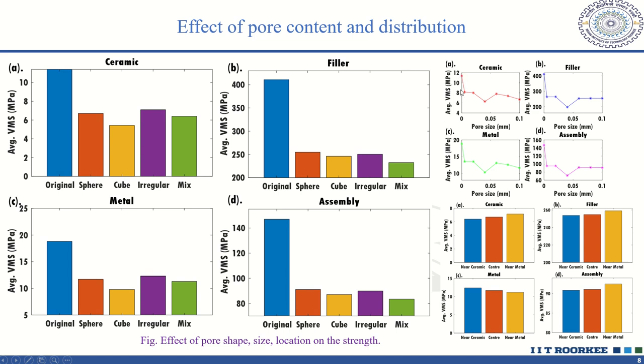And then the pore size is also varied from 0.01 mm to 0.1 mm, and it is found that the 0.04 mm pore size possesses the minimum average thermal stress. So we can say that 0.04 mm sized pores for a 0.2 mm base layer in thickness are the optimal pore sizes. And then the location of the pores is varied. Firstly, these are distributed near the ceramic material interface, and then at the center of the joint assembly, and then near the metal of the joint assembly. And it is found that the near ceramic location possesses lower average thermal stress, so these can bear higher ranges of thermal stress, and so these can be used.